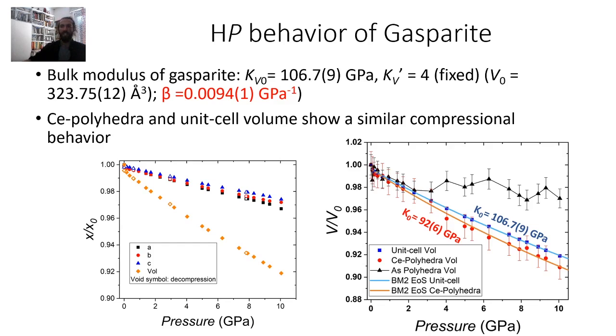As reported in the normalized volume versus pressure diagram on the right, the most important deformation mechanism responsible for the accommodation of bulk compression in gasparite is the volumetric compression of the RE polyhedron, represented by the red dots, and calculated from the refined structure models. In fact, fitting the pressure-volume data for the RE polyhedron with a second order Birch-Murnaghan equation of state yields a bulk modulus of 92 gigapascal.